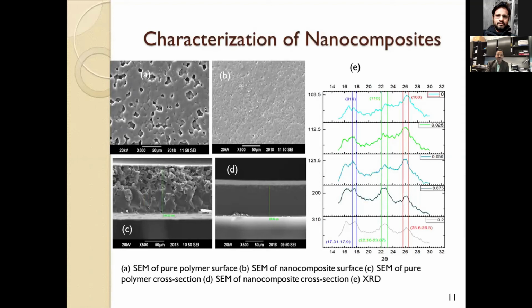Furthermore, we can see from the XRD pattern that when there is no filler added, there are no such sharp peaks. However, even the smallest amount of inclusion of the nanofiller gives rise to certain peaks at characteristic angles, as can be shown by the XRD patterns. This shows that not only was the boron nitride assimilated into the structure, it stayed there and it maintained its crystalline nature.